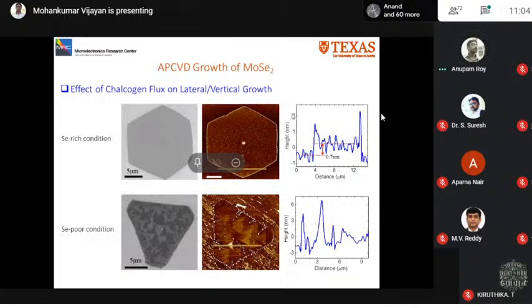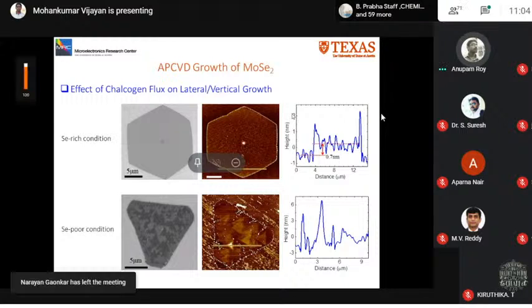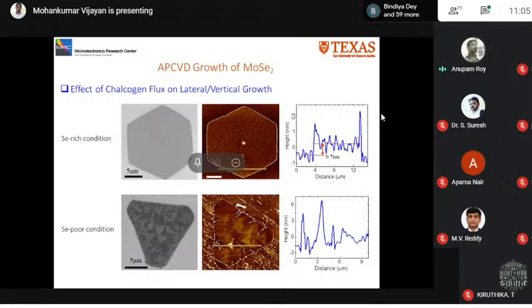Next slide. The images on the top show a uniform 2D single crystal MoSe2 domain grown in a selenium-rich environment. You can see from the line profile, the height profile and the line drawn on the domain, that it confirms uniform lateral growth. And the AFM image on the bottom shows several 3D island nucleation when we have a selenium-poor or selenium-deficient growth condition.